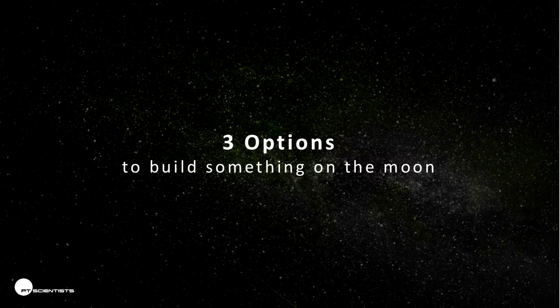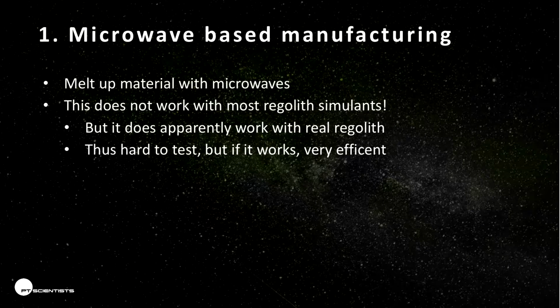There are three options, and one we like very much is microwave-based manufacturing. The idea is that you use an ordinary microwave, or the magnetron of it, and you melt the material because it contains some iron, and then you can get a solid surface. The problem is that the regular simulants used for testing rovers or spacesuits or anything alike, you can microwave them, but nothing happens, which is bad for testing.